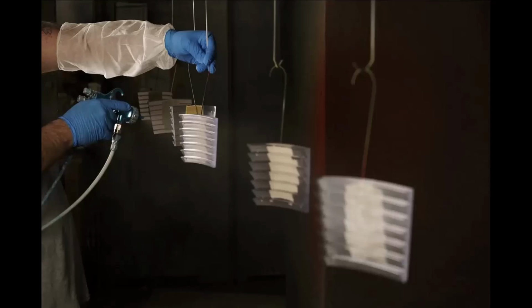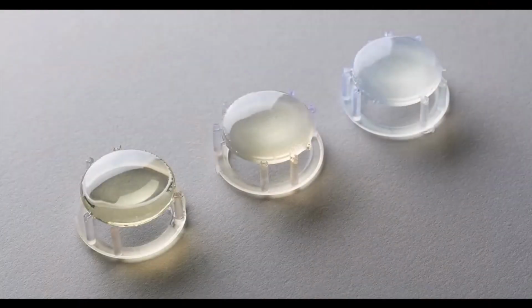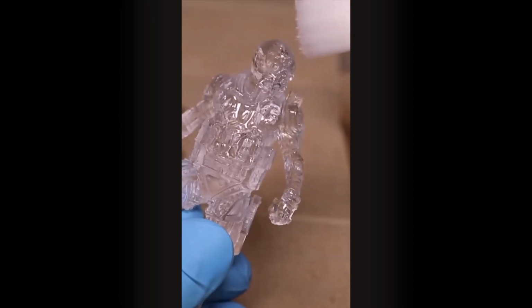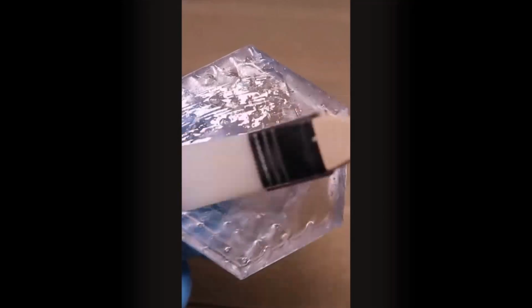You can use a general purpose 2K clear coat or an automotive clear coat if you want to go more professional. If you have a flat or nearly flat part, you can apply clear resin to the part by syringe, brush, or dipping. You can also technically apply clear resin to any of your parts. They don't have to be flat, but the flat ones usually showcase the clear result the best. Let the excess drip away and then cure it.